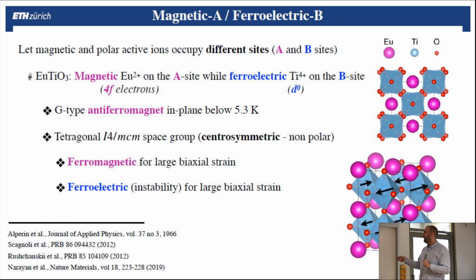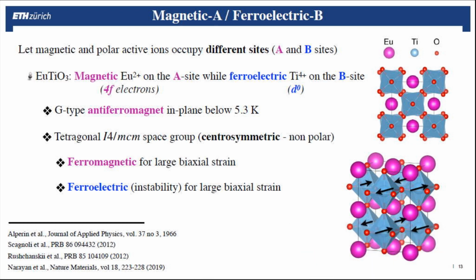So this material is an antiferromagnet in plane, and it's a G-type antiferromagnet. It means that if you consider one atom that has a net magnetization, the in-plane neighbor will have the opposite direction, and the out-of-plane neighbor will also have the opposite direction. So that means that overall, it's not magnetic, because everything is canceling out. And more than this, the symmetry of the structure, it doesn't matter the label here, is centrosymmetric, which means non-polar. But I told you it was an example of multiferroic. Actually, it is, because it becomes ferromagnetic instead of antiferromagnetic, and ferroelectric, but under large strain. So that means if you compress your material, then it will have these properties.